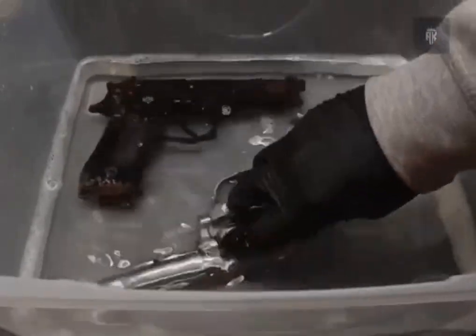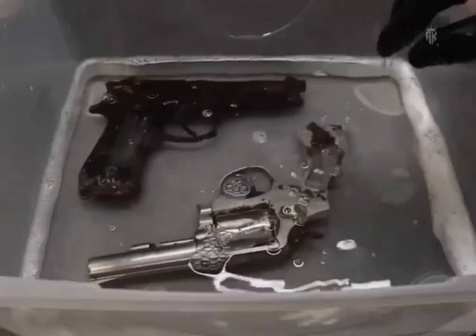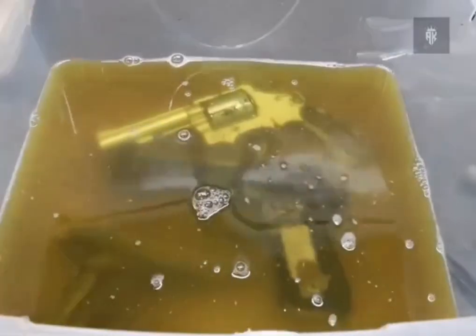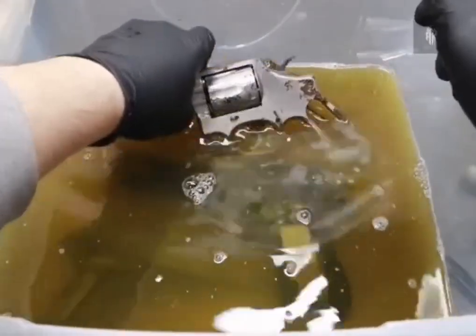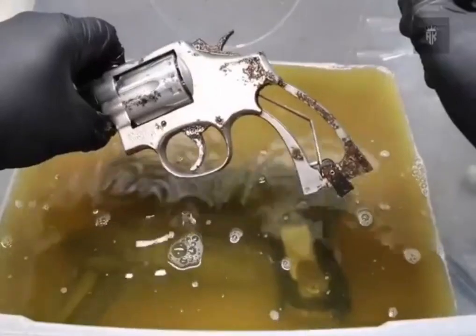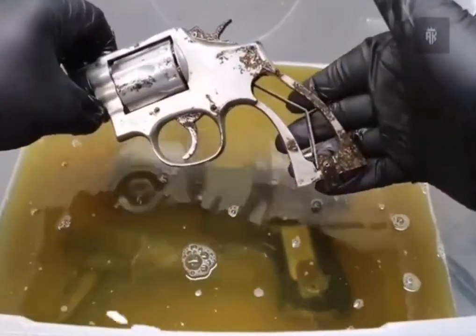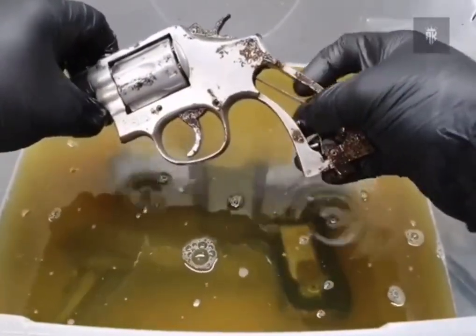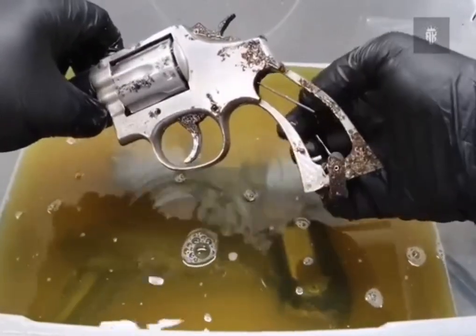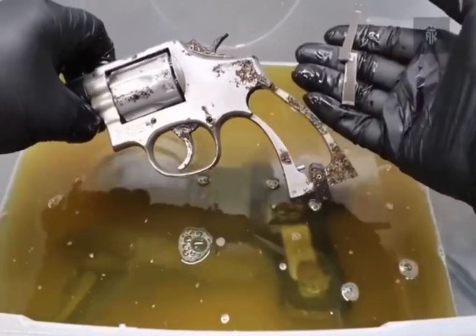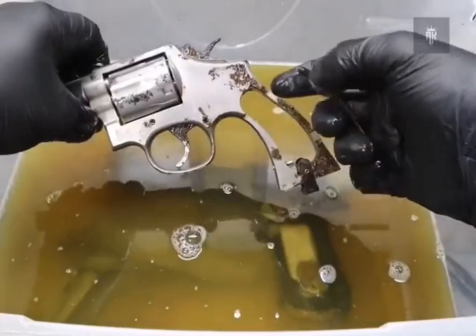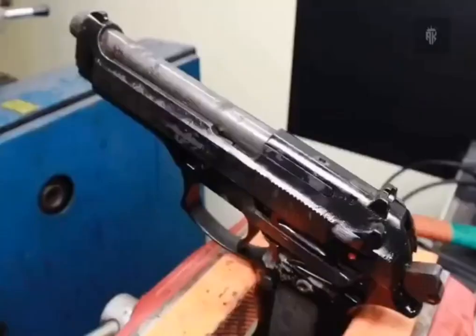I'm also dipping in the Smith & Wesson revolver, since that's stuck solid as well, and the Bernardelli for the umpteenth time. The next morning, I woke up to an unpleasant surprise. That thing you see in the revolver grip used to be the hammer leaf spring, and now it's in two pieces. I did a bit of research and found out that on their stainless guns, Smith & Wesson uses stainless steel even for the leaf springs, and some of these are susceptible to stress corrosion cracking if they're kept under tension in an aggressive environment. Probably the low pH of the bath was a factor.